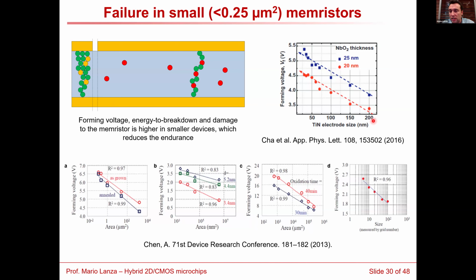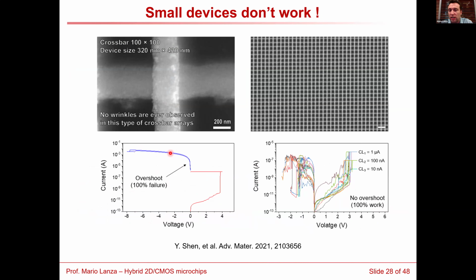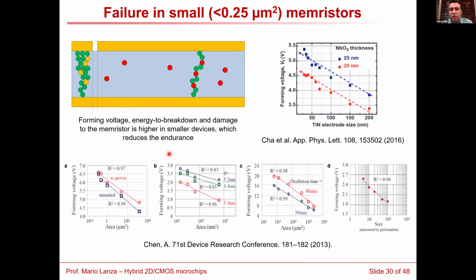When you go small in size, the breakdown field increases a lot for all devices, for all materials. And therefore, the energy to breakdown is higher and the size of the filament is larger. And therefore, this thing does not switch back, and it stays in a permanent low resistive state as you see here, okay? That's the reason why the small devices don't work.